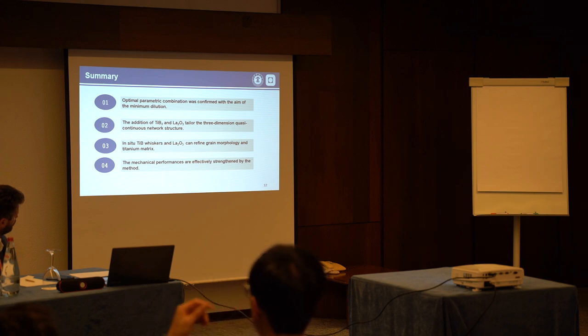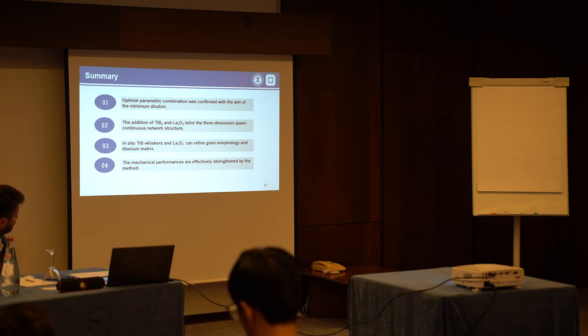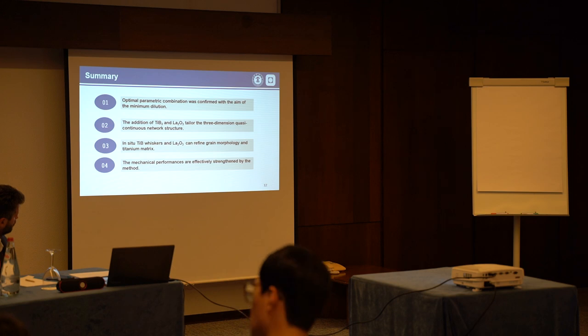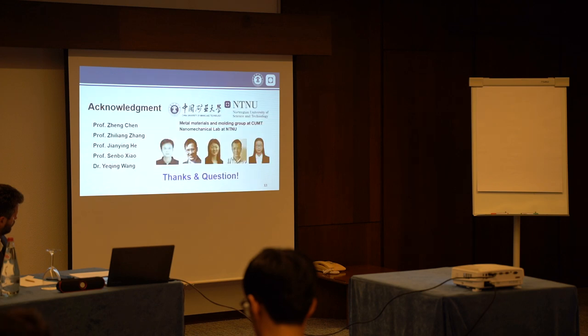The optimal parametric combination was confirmed with the aim of the minimum dilution. And the second is the addition of titanium diboride and lanthanum oxide tailored the three-dimensional quasi-continuous network structure. In situ titanium whiskers and lanthanum oxide can refine the grain morphology and the titanium matrix. The last is the mechanical performance is effectively improved. And thanks to the other supervisors at CUMT and NTNU.